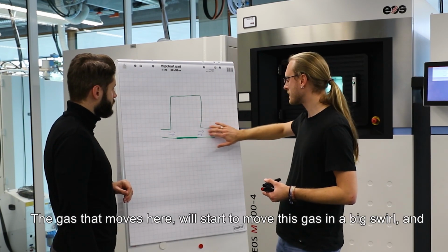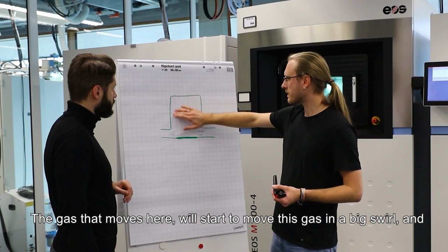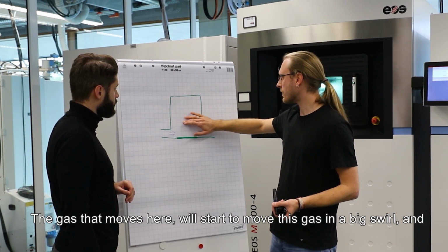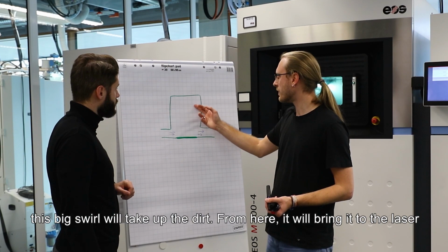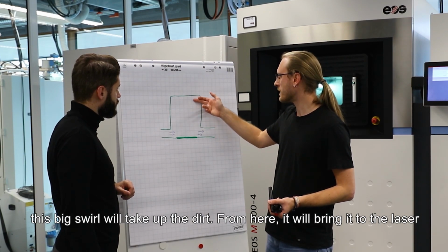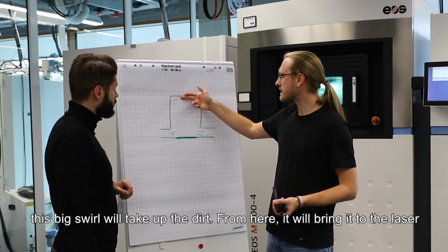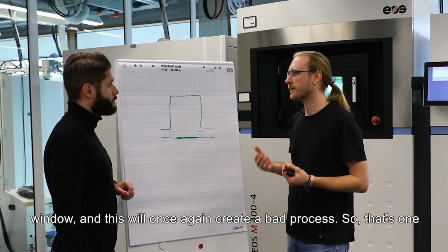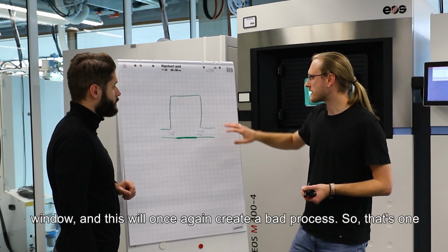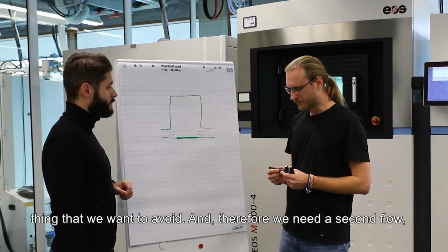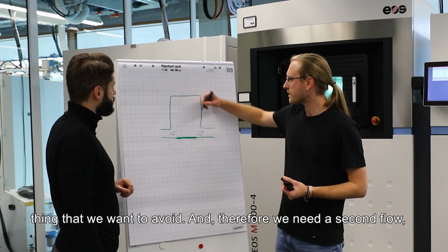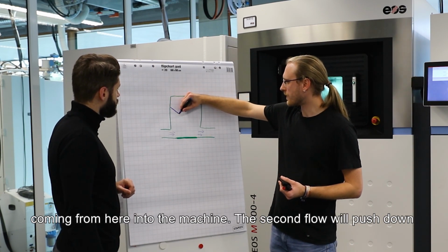The gas that moves here will start to move this gas in a big swirl, and this big swirl will take up the dirt from here, bring it to the laser window, and this will once again create a bad process. So that's one thing that we want to avoid, and therefore we need a second flow coming from here